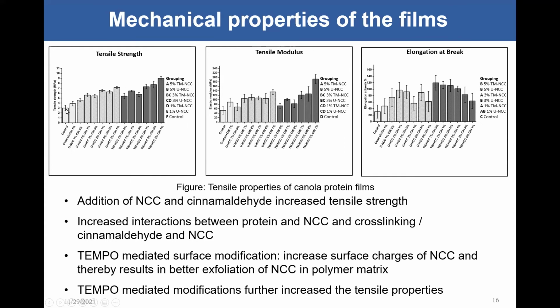So compared to that control, where they only had 3 megapascal strength, the new film with 5% TEMPO-modified nanocellulose, now you're talking about 9 megapascal strength. This is a significant enhancement of the material strength. When we talk about the tensile modulus, or the stiffness of the material, because when we apply a force to plastic, if it deforms, if it's not resistant to that deformation, then it's not good enough for the packaging material. Again, I'm not going to go into all of them, but as you can see in here, compared to the control, where there is an elastic modulus of roughly around 50 megapascal, once you add 5% TEMPO-modified nanocellulose, you can increase that elastic modulus almost up to 200 megapascal. So that's a very good improvement in terms of the stiffness of the material.